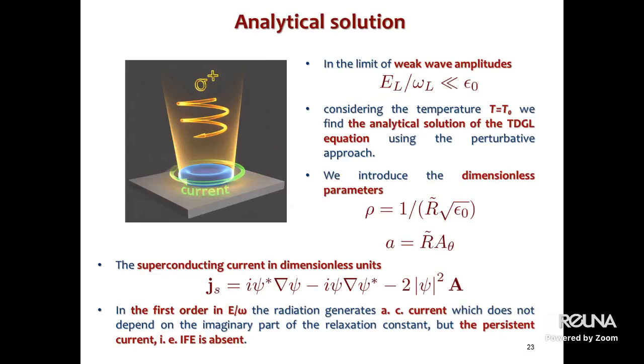First, let me talk about the analytical solution of this problem. In the limit of weak wave amplitude, weak meaning that the amplitude parameter, and by amplitude parameter I mean E divided by frequency, is smaller than the reduced temperature. Reduced temperature is simply 1 minus T divided by Tc0. It's the standard reduced temperature in superconductivity. And considering temperature close to Tc, we can find the analytical solution of the stochastic time-dependent Ginzburg-Landau equation by